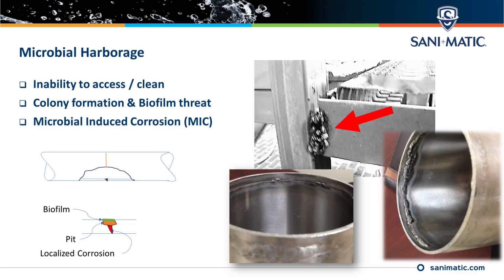You get those cracks forming, and then you can actually get MIC forming in the cracks of the chloride corrosion. All that being said, there's other things, little tiny cracks and crevices in these welds, particularly because the weld itself is more susceptible to corrosion because it's in a heat affected zone. It just creates an environment where you can have a lot of failures.